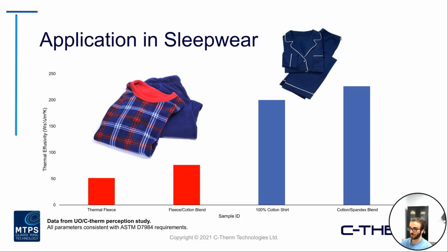Taking a look at the cotton t-shirt, again, about 3-4 times higher in effusivity. But then you can see the fleece cotton blend, not quite in the middle, but understanding here that the different mixtures of materials in these types of components can result in obviously different thermal responses. And by understanding how general materials will result in these types of measurements, you can again fine-tune your construction, your blend, to control the desired properties of interest.